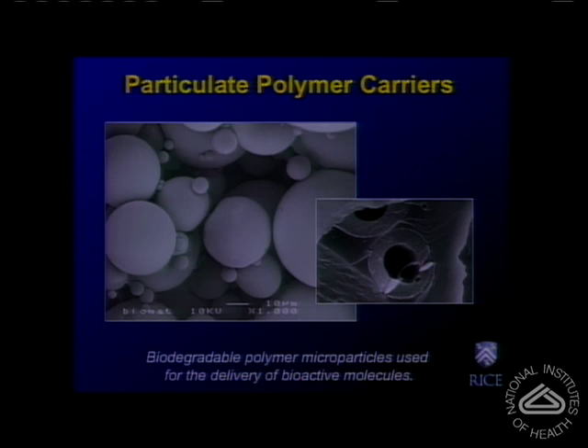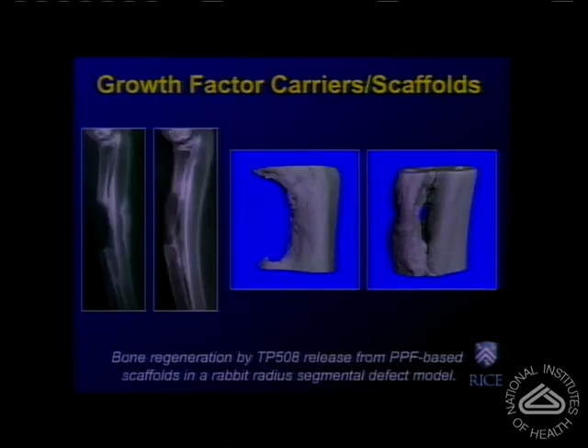This kind of system allows us to deliver bioactive molecules, and over the years, we and others have found that dose is a very important parameter that determines the biological response. But in addition to dose, what is equally important is the release kinetics. The same molecule can have a different effect if it is released in a controlled, sustained way compared to an immediate release fashion.